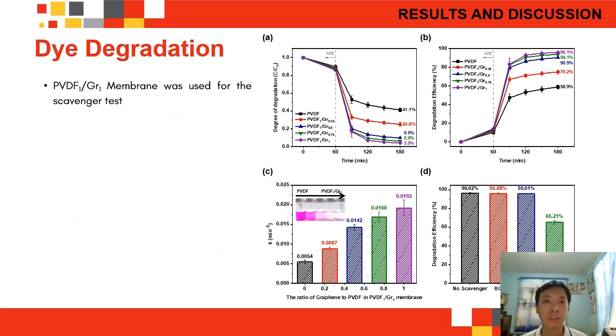Figures A to C depict the degradation efficiency of the toxic RHB dye through the piezo-catalysis process using the PVDF1 graphene X membranes. The results demonstrate a substantial increase in the dye degradation rate from 58.9% to 75.2% upon adding graphene powder to the PVDF membrane, and reaching 96.1% at the highest graphene content. The PVDF1 graphene 1 membrane was chosen as the optimal condition to investigate the mechanism of piezo-catalysis based on previous experiment results. The contribution of each free radical to the degradation process is shown in Figure 6D.